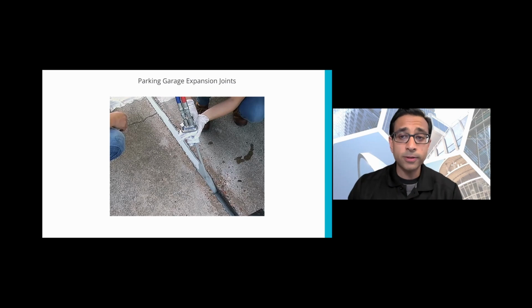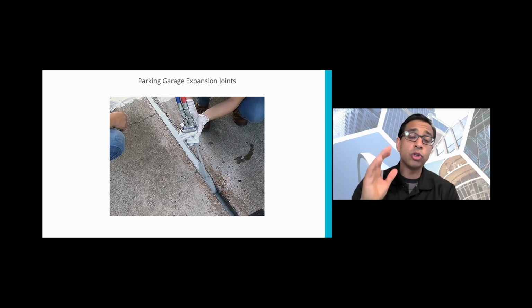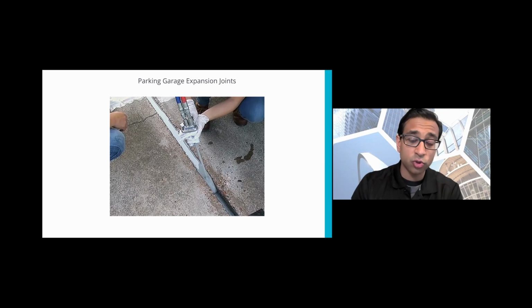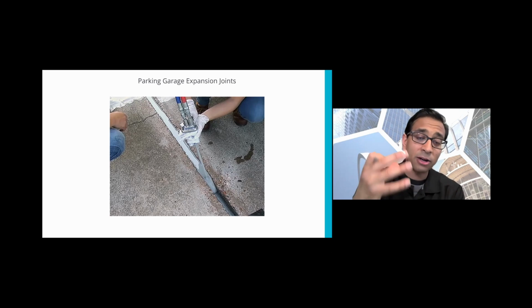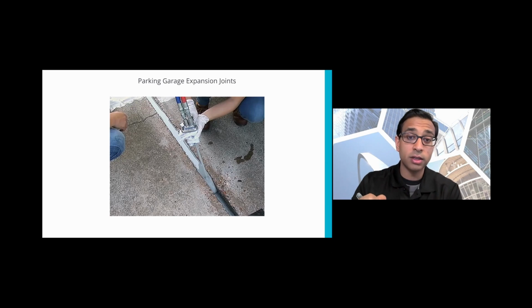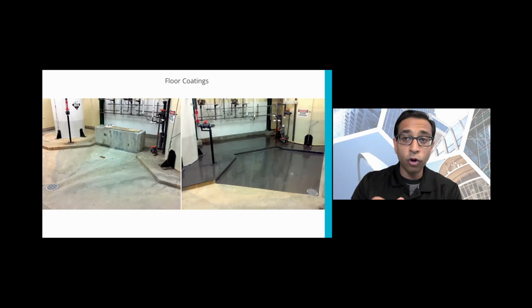So here's the deal. Epoxies are two parts and a filler. None of those components has water in it or a solvent in it. Okay. That means nothing is evaporating off. So when you use an epoxy system for your expansion joints in your garage, not only do they bond really well with the concrete, they don't shrink. They don't shrink at all. And because they don't shrink, guess what? You're not going to get any cracking. You're not going to get any of that crazy stuff that happens to the expansion joints when you use normal caulking systems. Floor coatings, finally.